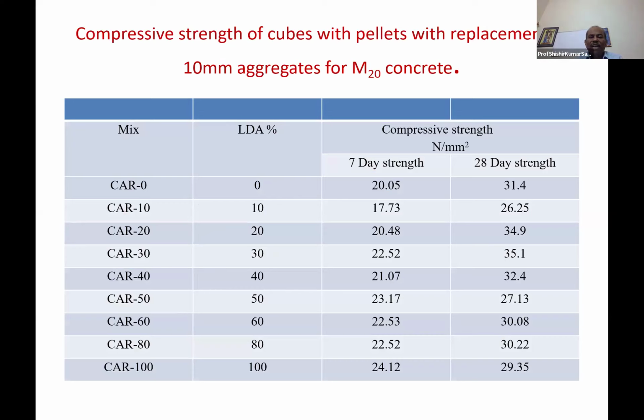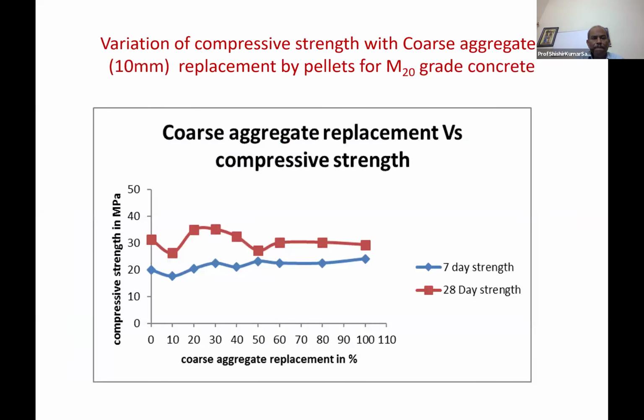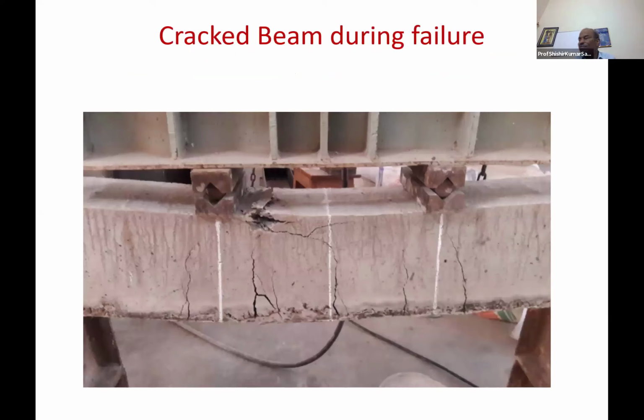Compressive strength of cubes with pellets with the replacement of 10 millimeter aggregates for M20 concrete. You can see 31, then 26, then 34, like this 35, 32. So a little abrupt trend when you do it with slag cement. Variation of compressive strength with coarse aggregate replaced by pellets, but it is showing standard strength comparable to normal aggregate. That way, we recommended it can be used.